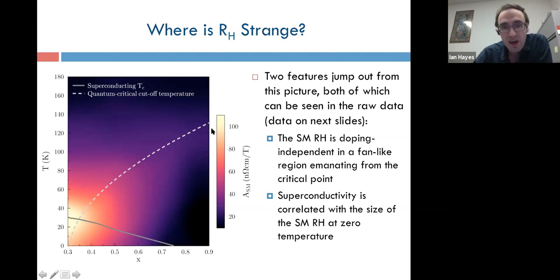And thereby traces out the kind of fan region that you would often draw when describing quantum critical systems with a single tuning parameter. So this looks very much like there's some detuning energy in the system that is getting stronger as we move towards higher phosphorus doping, such that if temperature is larger than that detuning energy, you simply get the same effect, independent of what your actual doping value is.